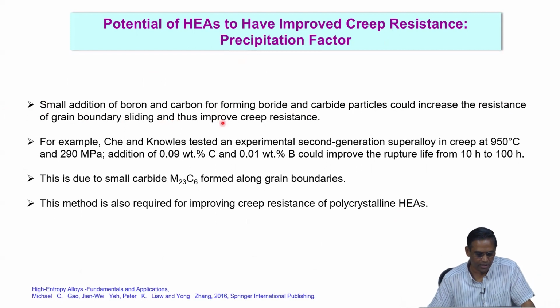For example, Che and Knowles tested an experimental second generation superalloy in creep at 950 degrees centigrade and 290 MPa. Addition of 0.09 weight% of carbon and 0.01 weight% of boron could improve the rupture life from 10 hours to 100 hours. So either you look at the creep strain or the rupture life. These are the two types of tests that high temperature people do, right?